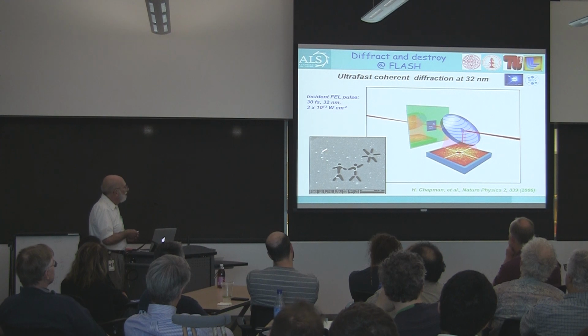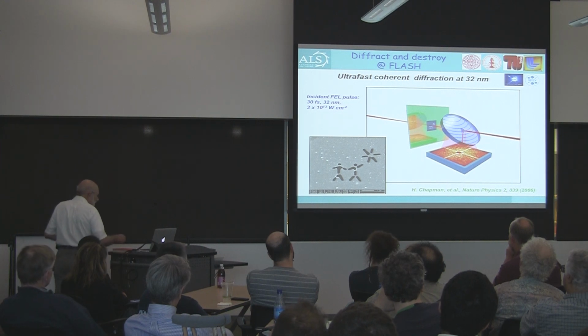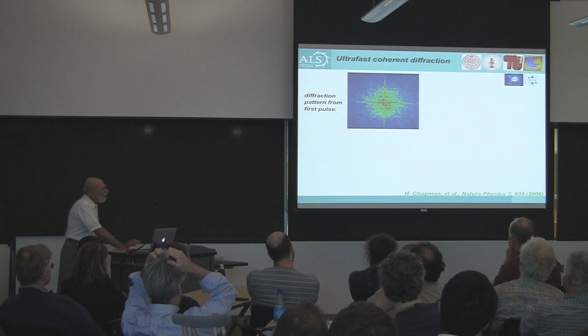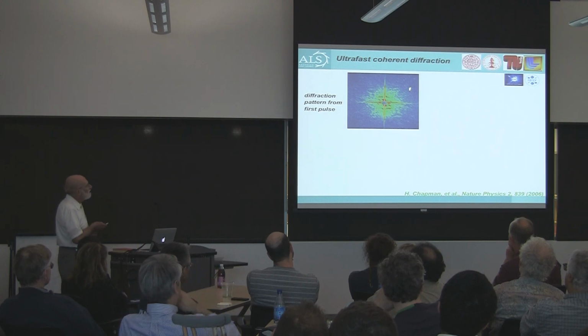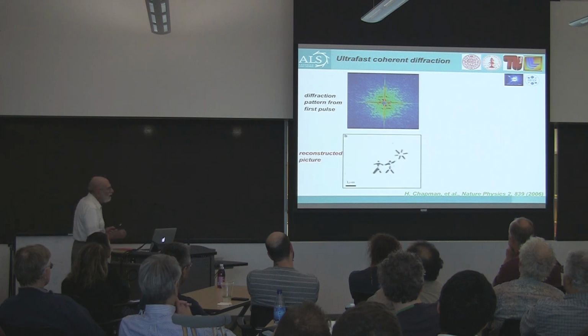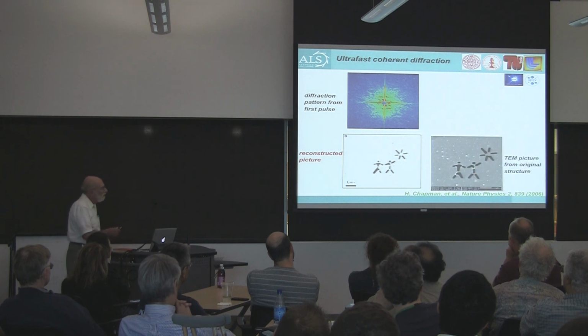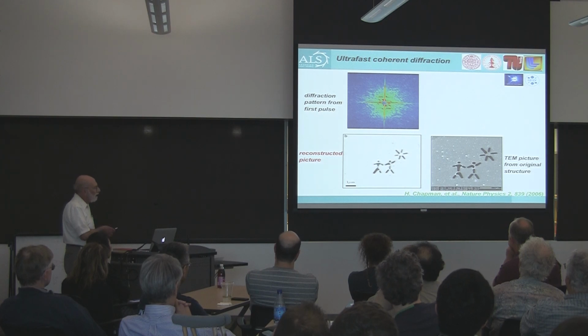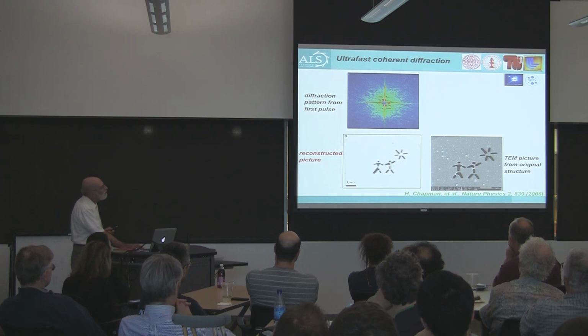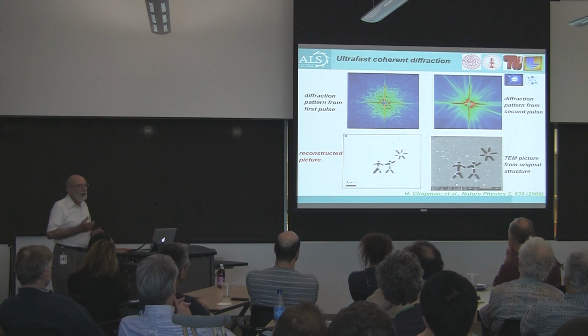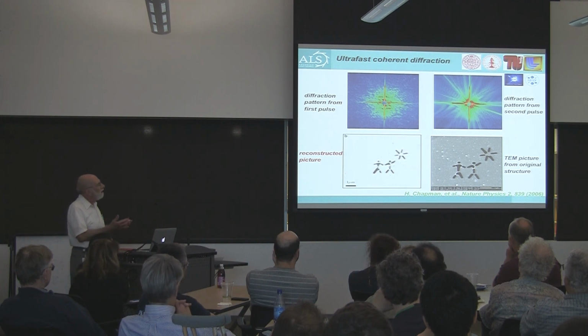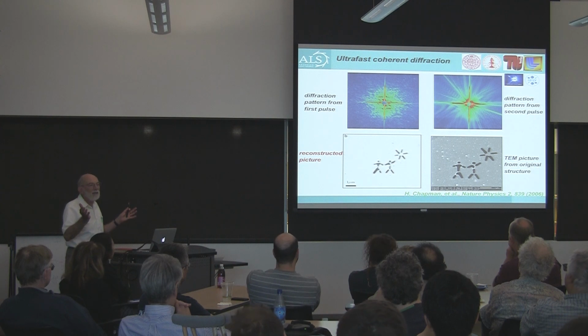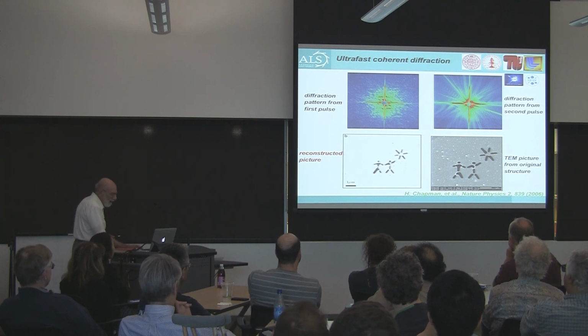took a little microfabricated object, hit it with a single pulse of the free-electron laser to collect the diffraction pattern. They were able to reconstruct it in a way that mimics the scanning electron microscope or the transmission electron microscope image. And if you record the next shot, you see that the thing is gone. Basically, what you are looking at is an empty frame.